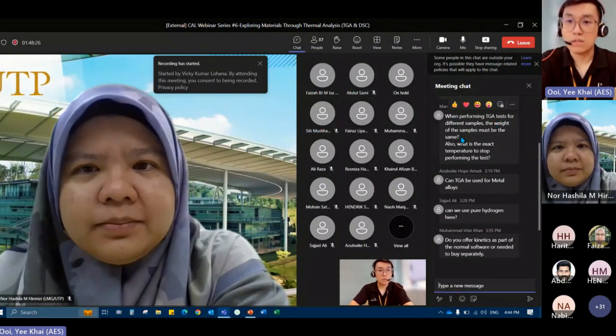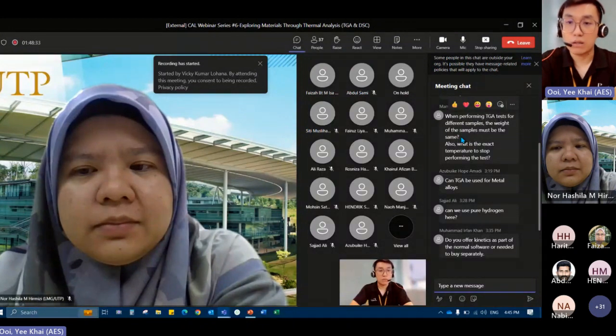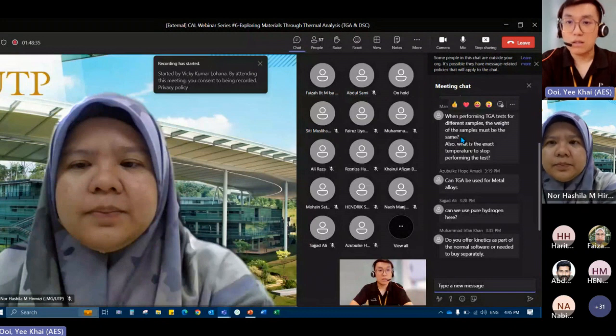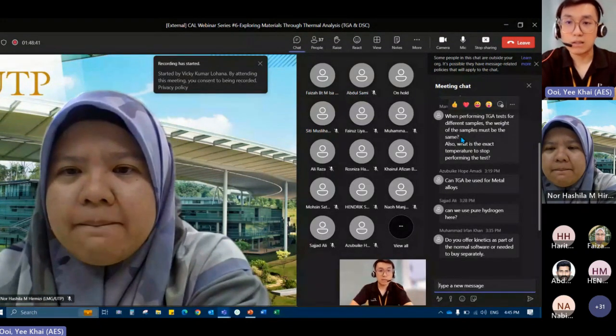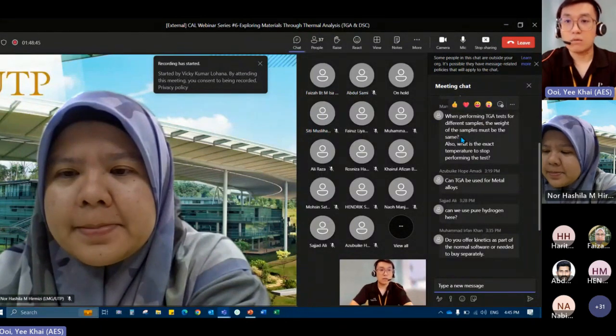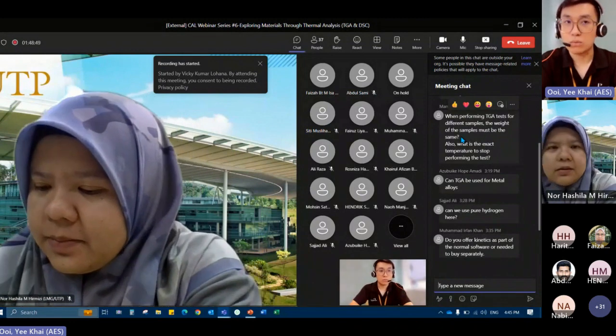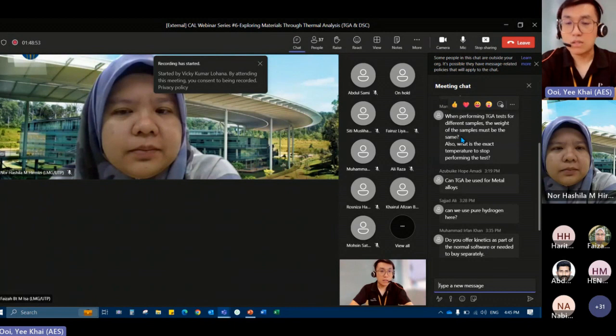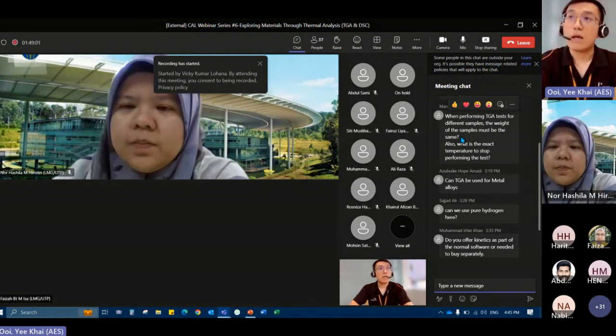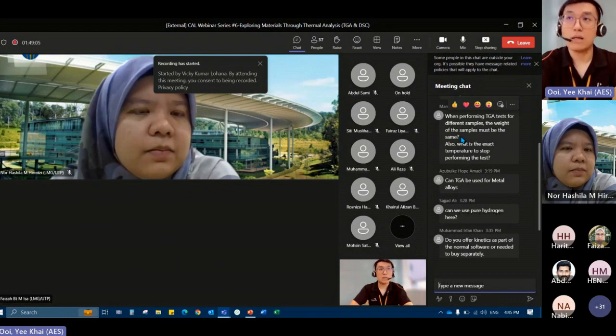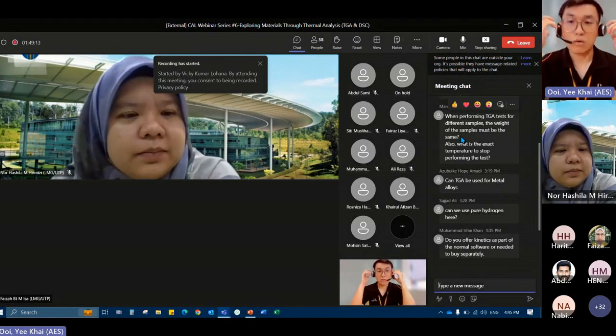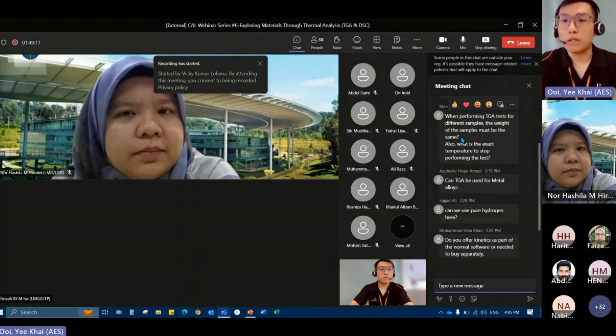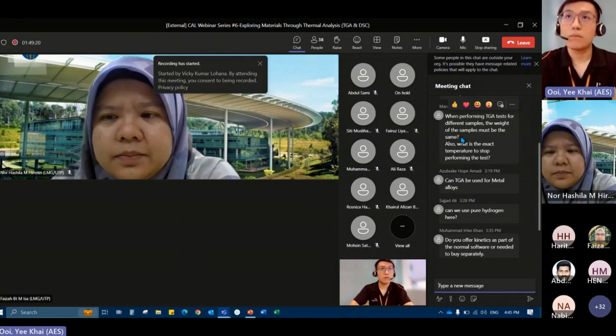No. If you just want to do a survey scan, for example, you don't need to do that. But for comparison studies, yes, please do that, because if you use a different weight of samples, especially a huge difference, then the result is not really comparable because it's going to have a different thermal lag and different resolution as well. So to make it simple, if you want to do comparison studies, or if you make it a habit, just run 10 or 15 milligrams of your sample, which is enough. It's not really encouraged to add a lot of sample into the run, especially more than 30 milligrams, for example. Even if you can do that, please don't, because you're going to introduce a lot of thermal lag, which affects the resolution, and the temperature profiling will not be accurate as well. You are going to affect the decomposition kinetics as well.